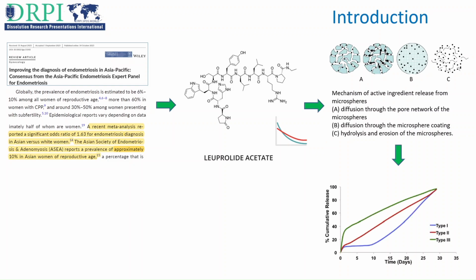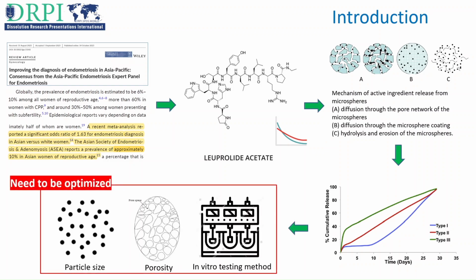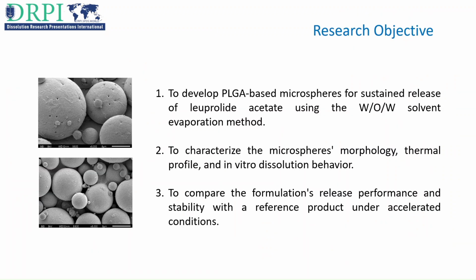Drug release profiles from microspheres can generally be classified into three types. Type 1 is initial burst release at low levels, followed by a lag phase and then sustained release. Type 2 is initial burst release at low levels, followed directly by sustained release without a lag phase. And type 3 is initial burst release at high levels, followed by sustained release. These release profiles are influenced by several factors, including particle size, porosity, and in vitro testing conditions, which became the optimization parameters in this study.